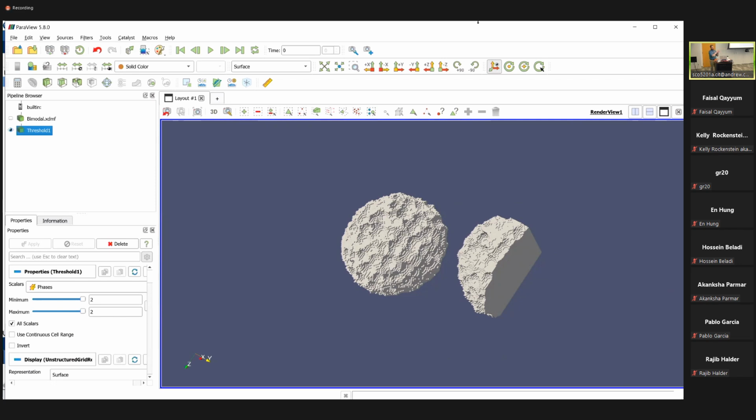And so you create the primary phase that, let's say, is highly textured. Maybe it's titanium and it's a region that has an extreme C-axis alignment, makes a microtexture region, as it's called. You would have that region be highly textured, and then you would have the surrounding medium primary phase, which you would insert in the inverse of the mask, be random texture. But people have done that. We've done that actually for the exact problem I just described, trying to create microtexture regions in titanium structures.